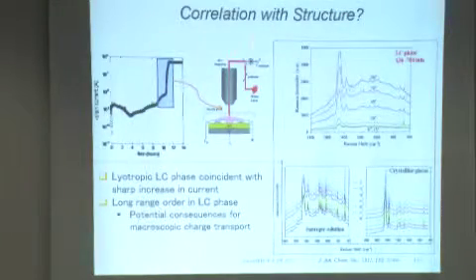All right, so we started looking at what happens during this interval where we see the largest increase in drain current in an evolving film of P3HT using Raman spectroscopy. And what Mohan and Min-Sung Park, Mohan's student, found is that by doing polarized Raman measurements, they saw characteristic features of a liquid crystalline phase at a given point during the solvent evaporation process.